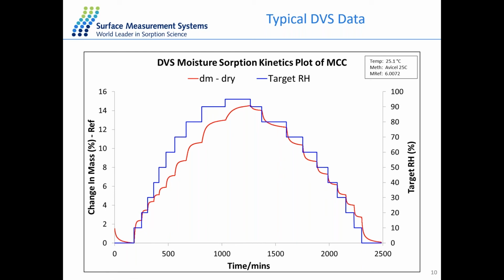For this microcrystalline cellulose, because the uptake is more than 10%, it has a very significant uptake of water. So we just need to use a very small amount of sample, around 6 milligrams, to already get very good quality water sorption data. The total uptake for this microcrystalline cellulose is about 14%, and the total experimental time is about 2 days. And that's just the sorption kinetics of this microcrystalline cellulose from the mass plot.